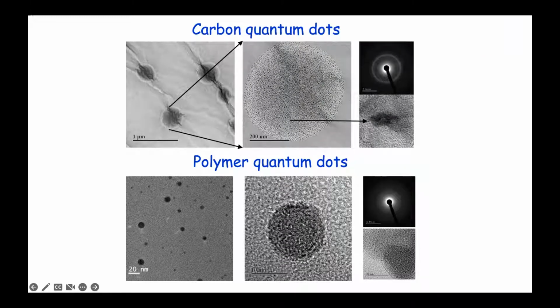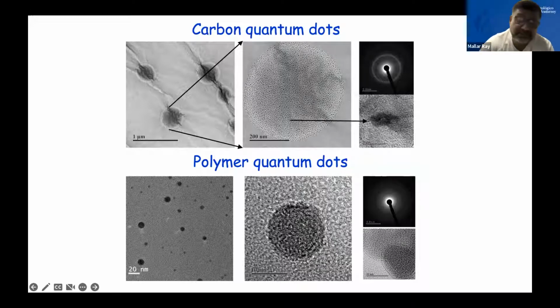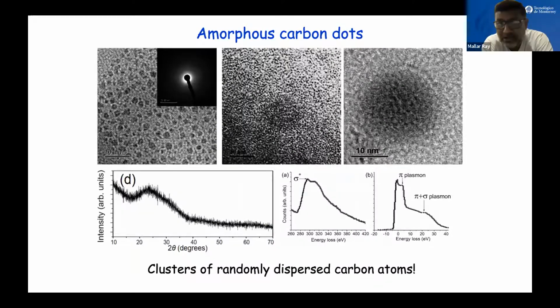Now, polymer quantum dots can be crystalline, or may not be crystalline. Both of them are possible. If you have a long polymer chain rolled up in a manner which induces some kind of periodicity, you get a crystalline signature. Or a ball of wool just crumpled together, you don't get a crystalline signature. But nevertheless, they are essentially polymers. They are long chain carbon molecules. Whereas in case of amorphous dots, if I just look at their TEM images, it will be very hard to distinguish them from the graphene dots or even the carbon quantum dots in certain cases.